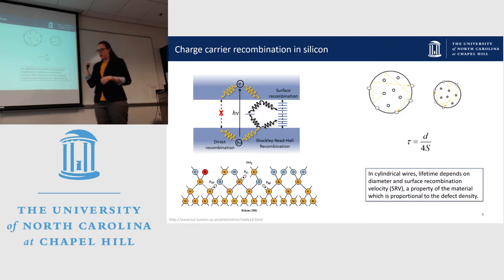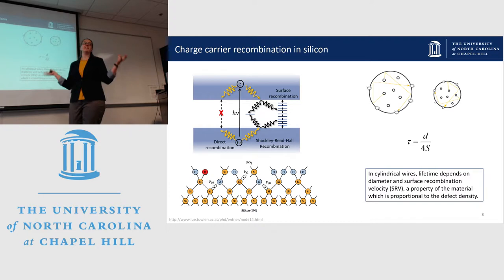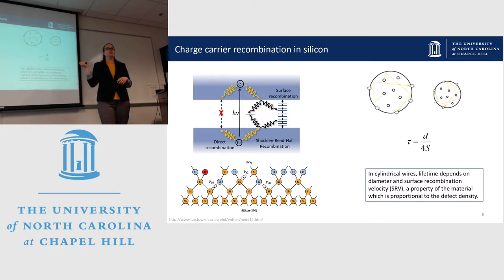Now, for people who are making devices out of silicon nanowires, solar cells, transistors, sensors, anything like that, the quality of the surface is really important. And so it's really useful to be able to quantify that and say, this wire has a quality that is described by some number. Turns out that number is S, which stands for the surface recombination velocity. And that's proportional to how many defects there are, or how many of these recombination centers there are at the surface. So more defects means a larger value for S.